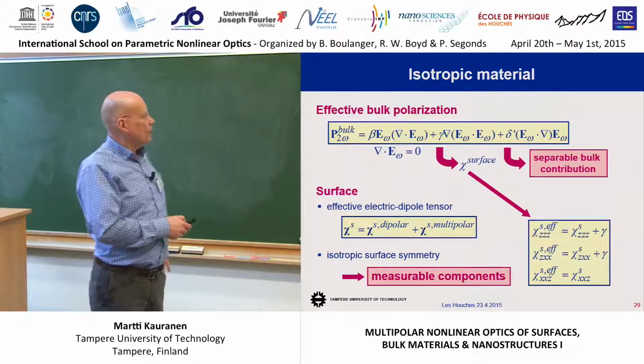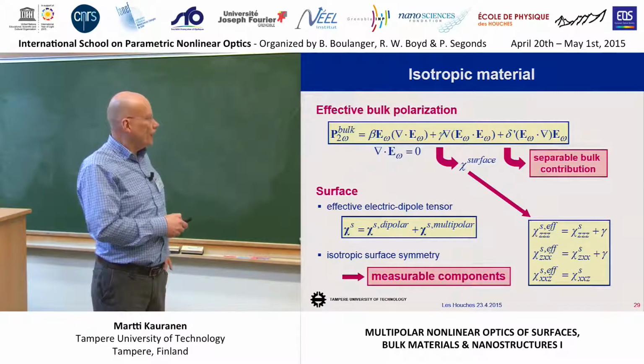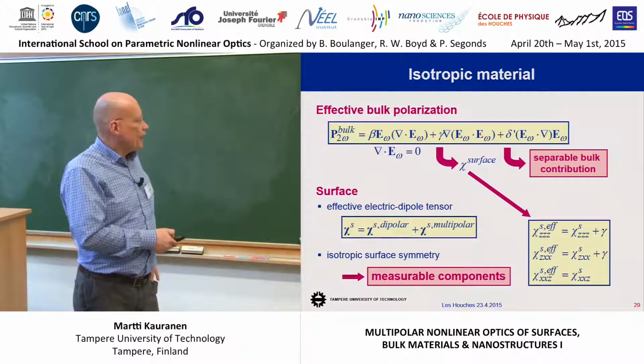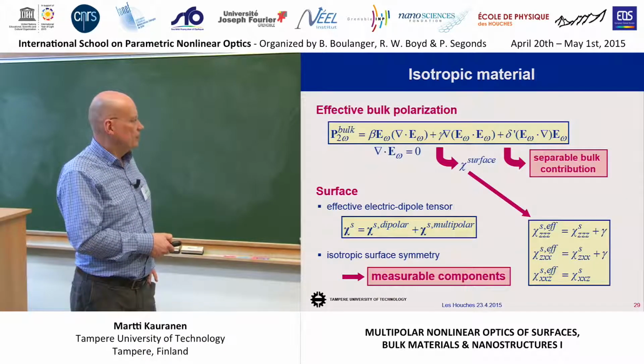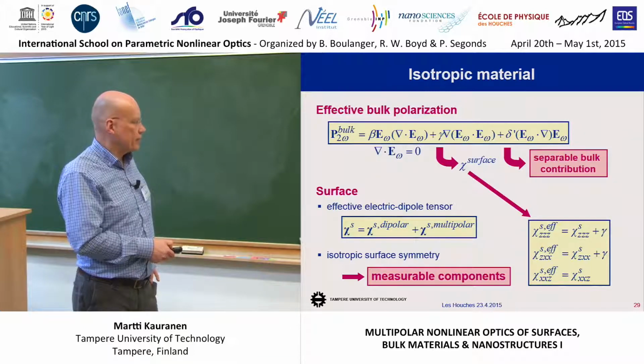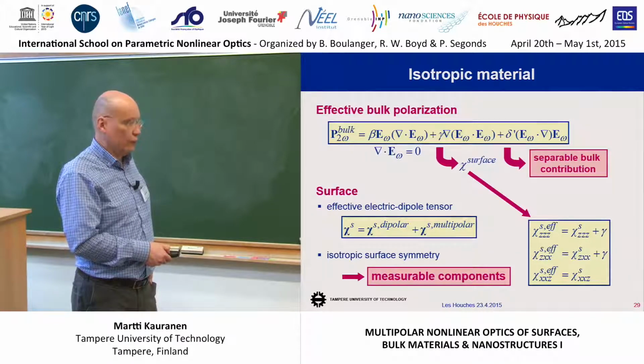And when you look at the details of all these treatments, you find out that the effective surface component with indices z, z, z is the true surface response with the same indices plus gamma, which is the bulk parameter. Okay? The same happens in zxx, so it's the true surface parameter component zxx plus gamma. But this gamma does not contribute to the xxz surface component.